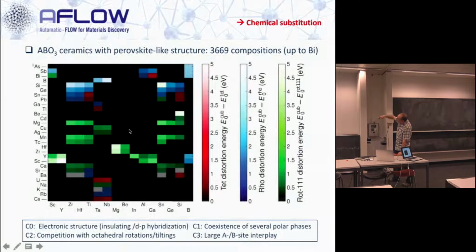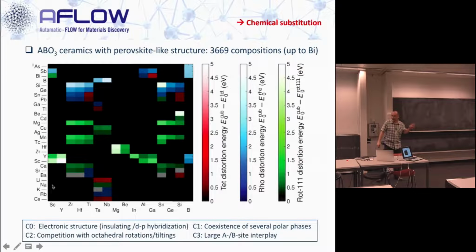This is a map that represents red for the tetragonal distortion, when the tetragonal distortion is minimum, rhombohedral is blue, and rotational is green. So you can see immediately that most of the tetragonal, the red ones, are very sparse. So there are not a lot of tetragonal materials. And some of these we knew from the beginning are unrealistic. Lithium is a hypothetical perovskite. It's not a perovskitic material. Lithium niobate, for instance, is not a perovskitic material, right? So some of those are fictitious. They were just hypothetical. So the black ones correspond to materials that don't satisfy criterion number 0. So they are not insulators. They don't have this hybridization.